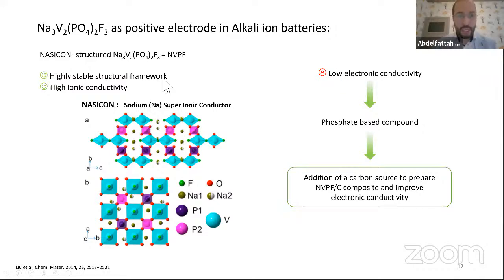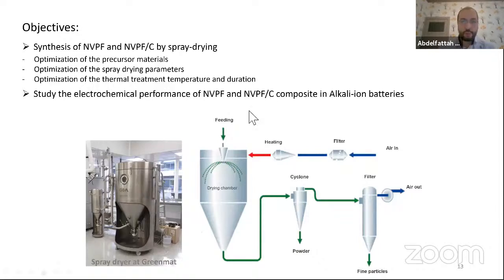The main drawback of this material, as with phosphates in general, is its low electronic conductivity. But by using the spray drying method, we can prepare this composite material in one step by adding carbon sources to the suspension of the precursors. When we spray dry it, we prepare this composite material in one step. Indeed, for that, we have to make different optimizations to prepare a pure and well crystalline material. We have to optimize the precursor materials, the spray drying parameters, and also the heat treatment, to prepare pure material without significant impurities, which is one of the main factors that determine the electrochemical properties of the material.